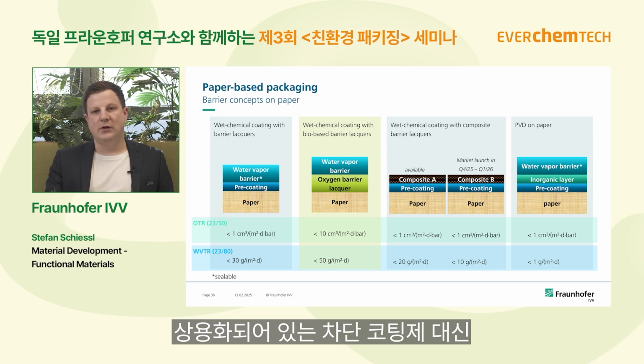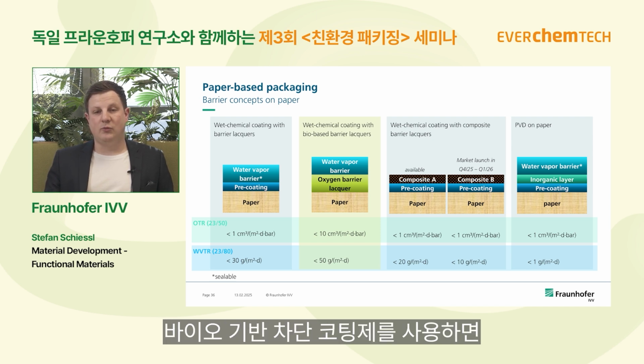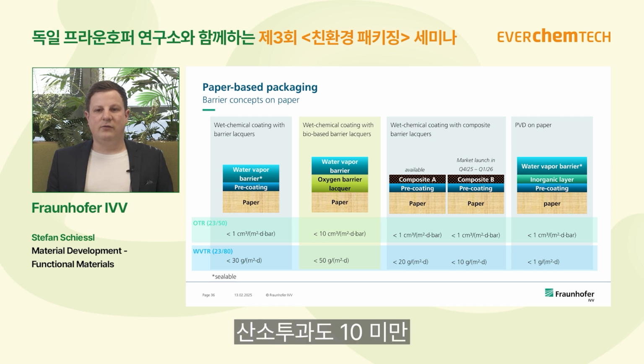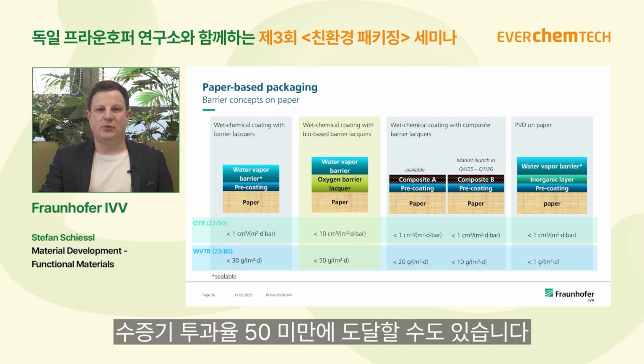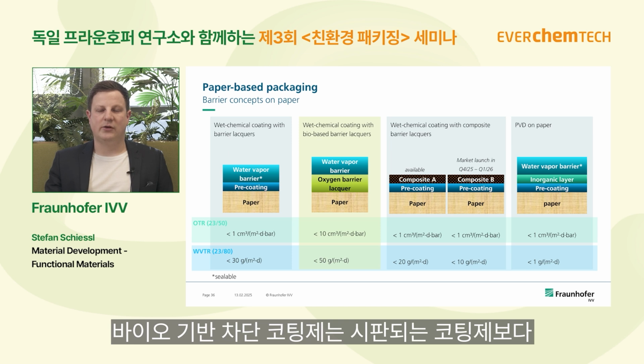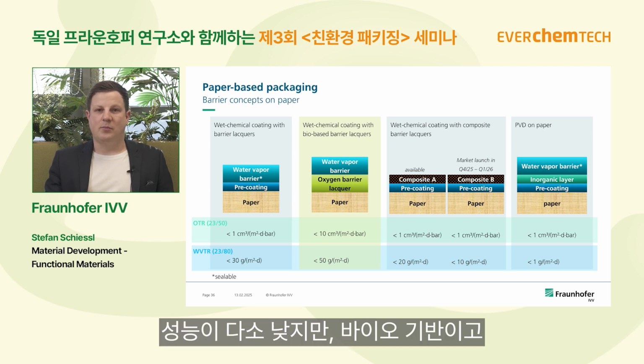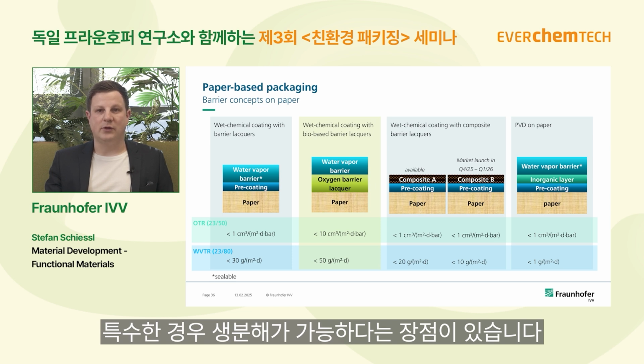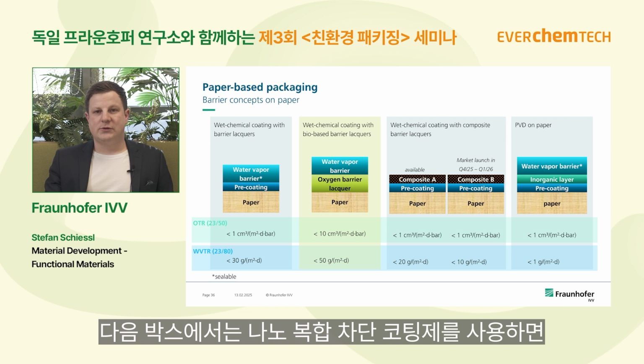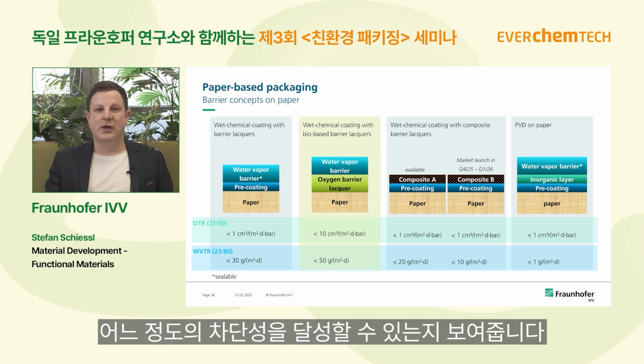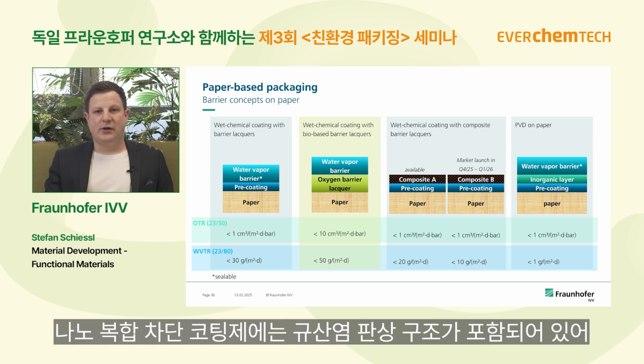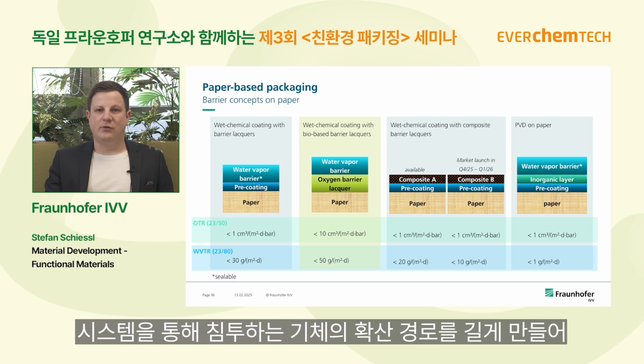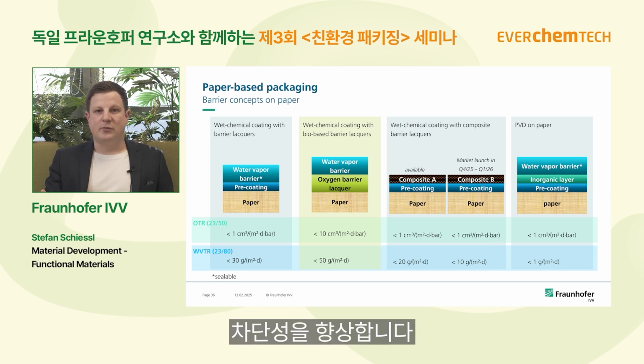If we move from a market available barrier lacquer to a bio-based barrier lacquer, then we can even reach oxygen transmission rates below 10 and water vapor transmission rates below 50. So we are not as good as the market available lacquers, but we have the advantages that we are bio-based and we are biodegradable for some special cases. In the next box you see which barrier properties are possible to reach with a so-called nanocomposite barrier lacquer. This barrier lacquer contains silicate platelets that improve the diffusion path for the gases permeating through the system, and this even improves the barrier properties.